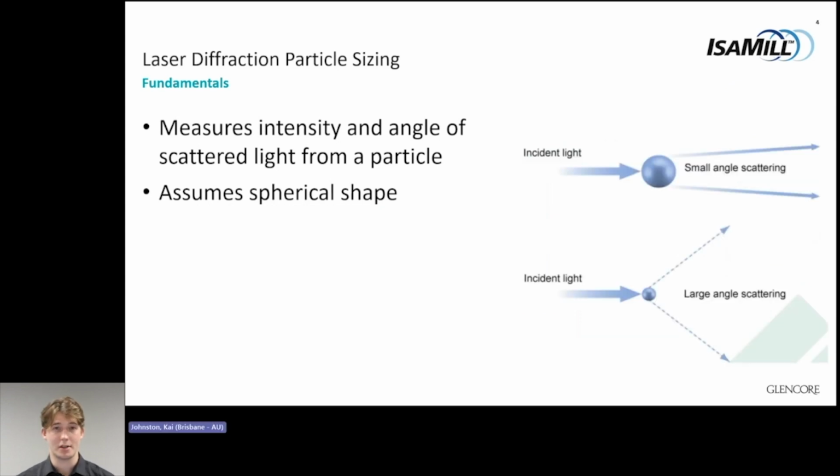So how does the laser sizer measure the particle? Well, it relies on the angular variation in light scattering as a particle passes through a beam. Coarser particles, as pictured, scatter light at smaller angles with greater intensity, while finer particles scatter light at weaker intensity and larger angles. Both angular variation in light and intensity is measured to determine a volume, and this is converted to a volume equivalent sphere. Because of its accuracy at measuring the sub 38 micron particles and its ability to achieve consistency, this has become the gold standard for sizing in stirred milling tests.